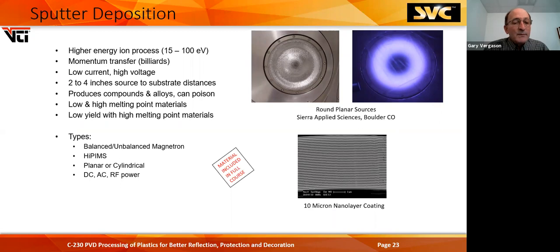Taking a little look at sputtering, a higher energy ion process, about 15 to 100 eV. It's a momentum transfer. You've got a high voltage on the surface of the cathode. You're ionizing the argon gas that's in there. The gas ion hits the surface of that sputter target and sputters out a metal ion. Usually your coating distance is 2 to 4 inches from the target to the substrate. It can be used to produce compounds and alloys.